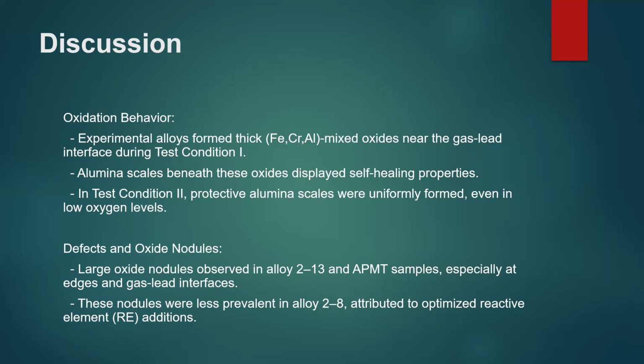Defects and oxide nodules, including large oxide nodules, were observed in alloy 2-13 and the APMT sample, especially at the edge and gas-lead interface.